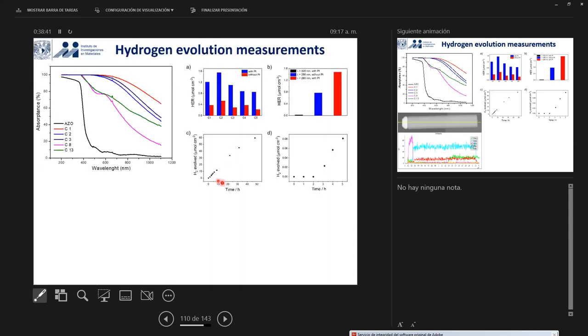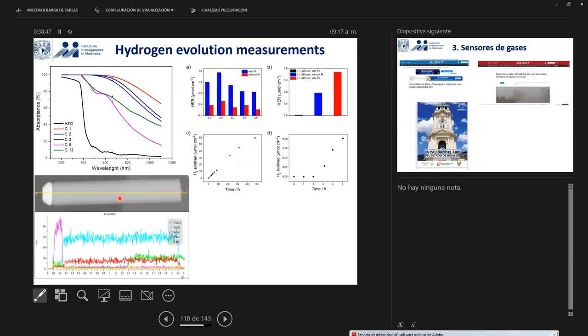And these structures were quite stable. We measured up to 50 hours, and the response was quite stable and good. And again, this is one of the mappings we have done for studying the composition of these nanowires. And we found that this whole structure up to here is zinc oxide. And on the tip, we have gold.